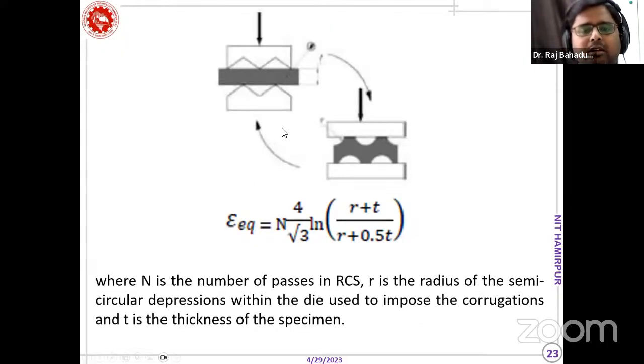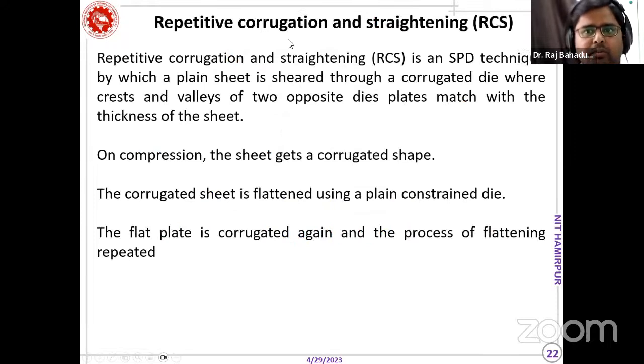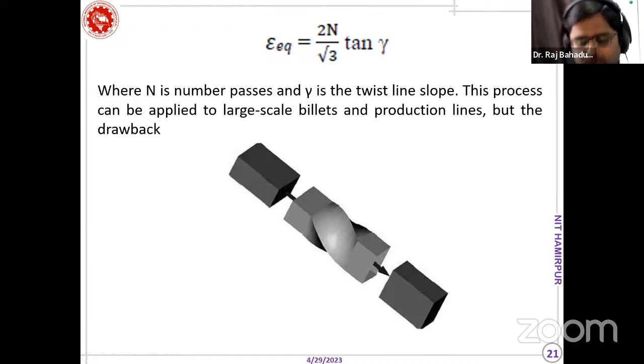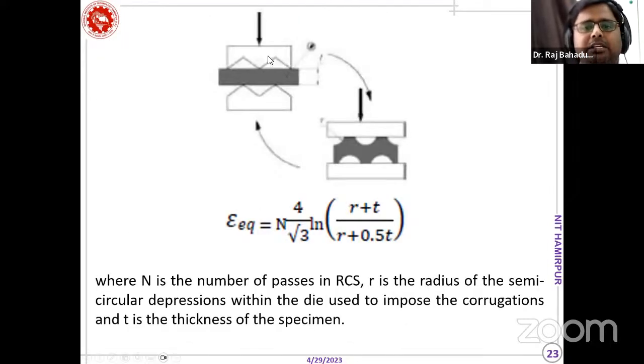So this is again a new technique, repeated corrugation pressing and straightening. In that process, we have a sheet or material. We press it, and after pressing we will have this kind of shape of the sheet. And again you deform that material by flat dies, and you will have the similar kind of material. Essentially this whole process is in a closed cavity, otherwise there is a chance of expansion of the sheet, and then we cannot maintain the cross section of the material. So this is the formula by which we can calculate the equivalent strain during this process.